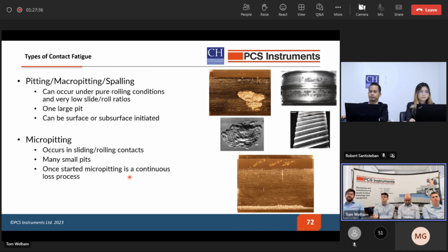So rolling contact fatigue is made especially difficult to study because it has a large number of influencing factors, such as material, the geometry of the contacting bodies, pressure, the lubricant, the roughness, and of course you have sliding in the contact as well, which applies this shear force, which pulls the surfaces apart and creates the cracks and the pits that we see in bearings and gears.